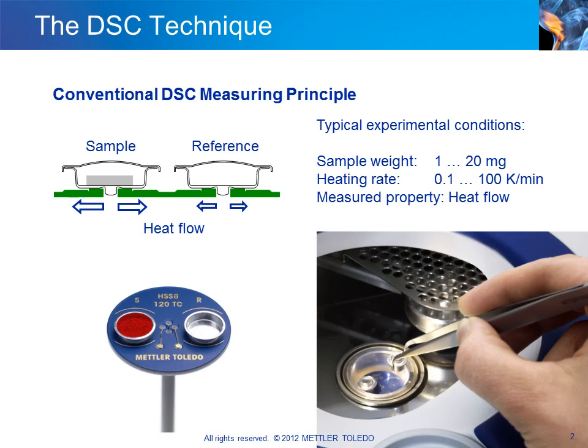The slide illustrates the most important aspects of the conventional DSC technique. The sensor has two separate measurement positions. One is for the sample and the other for the reference. The sensor is located in a furnace whose temperature is precisely controlled. The measurement system is several centimeters in diameter. Samples typically weigh 1 to 20 milligrams and are enclosed in a small crucible. The reference sample is usually an empty crucible.